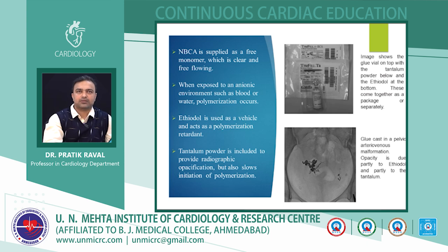The NBCA is supplied as a free monomer which is clear and free flowing. When this NBCA is exposed to an anionic environment such as blood or water, the monomer starts polymerizing and forms a permanent glue. Ethiodol is used as a vehicle agent and it also retards premature polymerization. Tantalum powder provides radio opacity and also retards the polymerization.